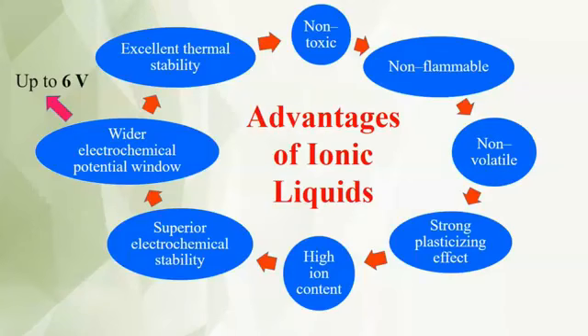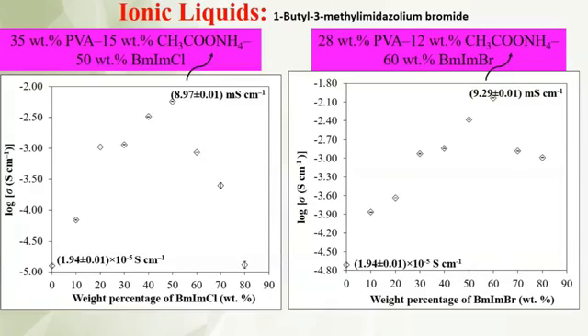Okay, next we're going to look at some of the properties of the ionic liquids. When we use ionic liquid as a conductivity enhancer in the polymer electrolytes, we can avoid using environmentally non-friendly solvents like organic solvents. And this ionic liquid also can give us excellent thermal stability and high ion content. So these results show that the incorporation of ionic liquid can increase the ionic conductivity of the polymer membranes. This result shows the usage of the 1-butyl 3-methyl-imidazolium bromide.